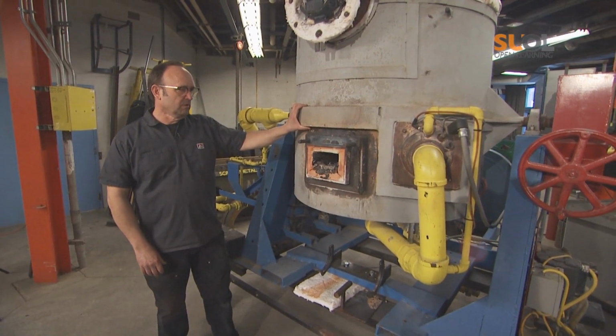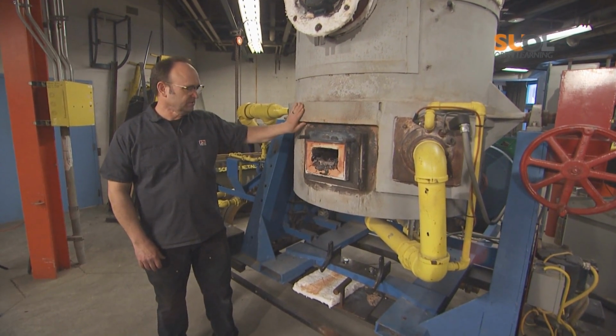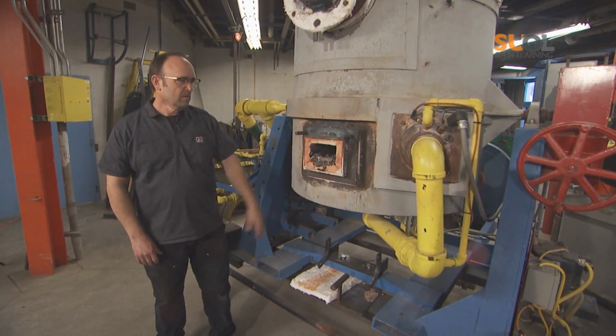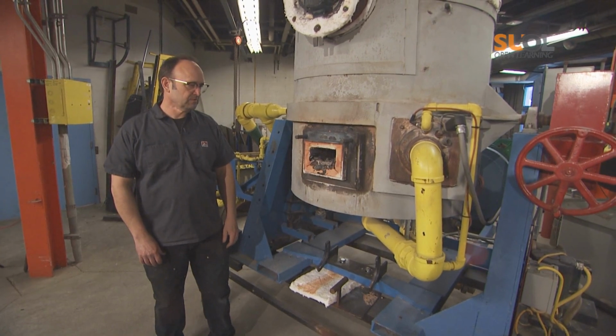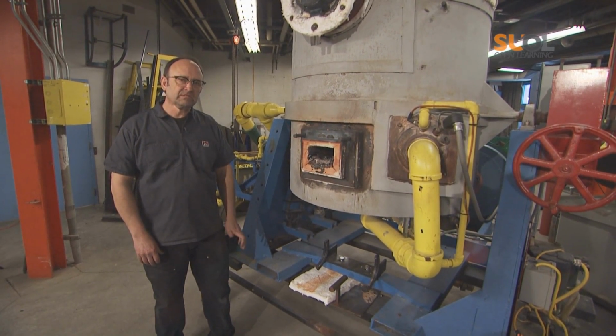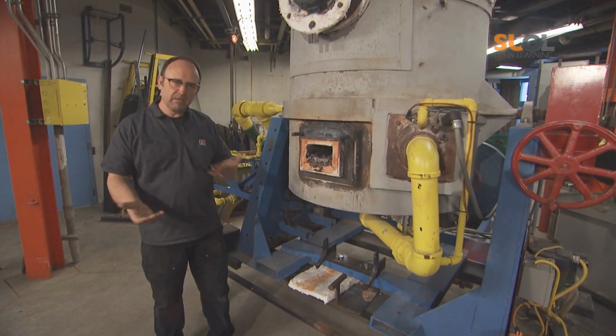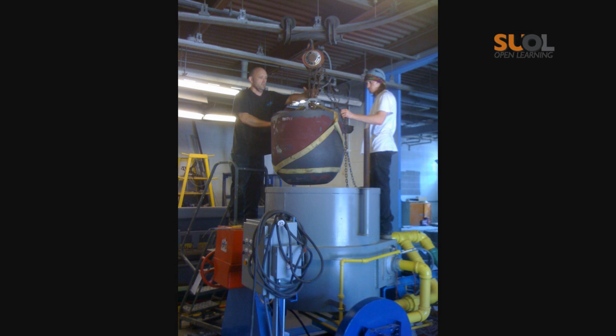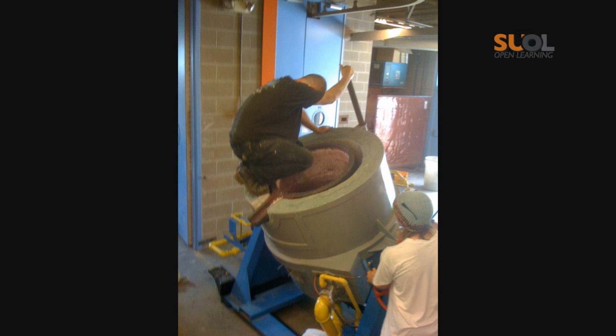We graduated to a much larger size furnace. This has been the workhorse of the Syracuse University Lava Project. It's a natural gas-fired bronze furnace I picked up used in Canada, and we've rebuilt it to make lava. It has a ceramic-like lining. It's a crucible made out of graphite and silica sand. It withstands temperatures of 3,200 degrees Fahrenheit. It's lined, so that would be that ceramic portion inside. That's where the lava is melted and contained.